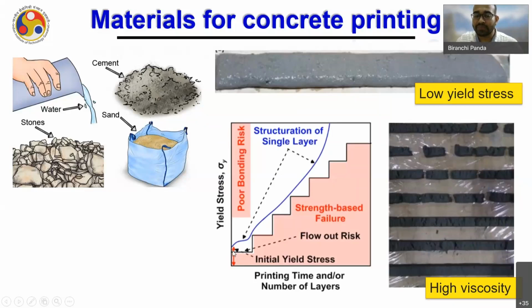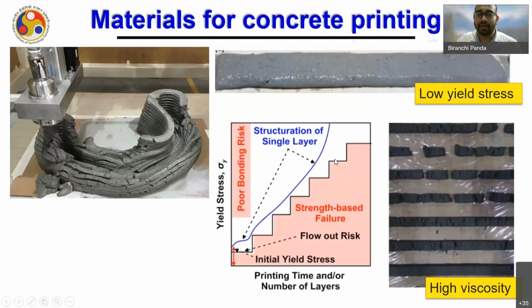But if the yield stress is very high, then what is going to happen? We are going to have an issue of poor bonding risk. And if the yield stress is very low, then after printing 2 or 3 layers, it is going to collapse, as shown in this picture. So we need a minimum yield stress. If the yield stress is very low, then after printing a few layers, it is going to collapse.